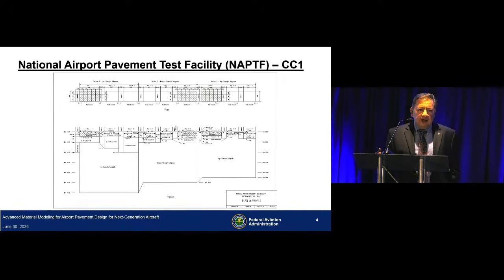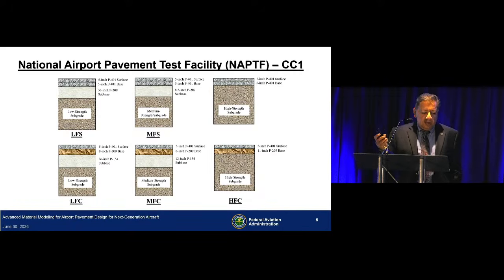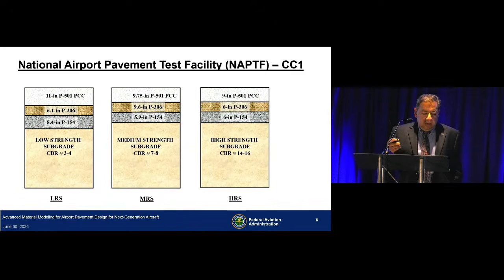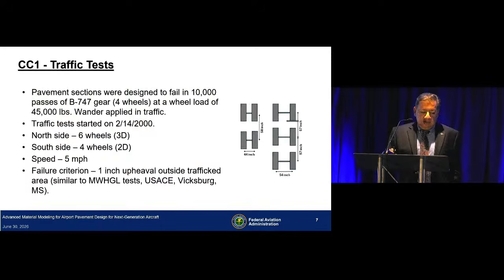There were 3 different subgrade types: low strength, medium strength, and high strength. And there were 3 test sections built on each of these subgrade types: 1 concrete and 2 asphalt pavements, 1 with a stabilized base and 1 with a conventional aggregate base. And this slide shows some of the cross sections. Now you will see that the pavement cross section thicknesses are different. And the reason for that is all the asphalt pavements and the concrete pavements were designed to fail in 10,000 passes of a Boeing 747 gear at a wheel load of 45,000 pounds. So the loading condition was the same for all, the subgrade conditions were different, and that resulted in different pavement thicknesses.